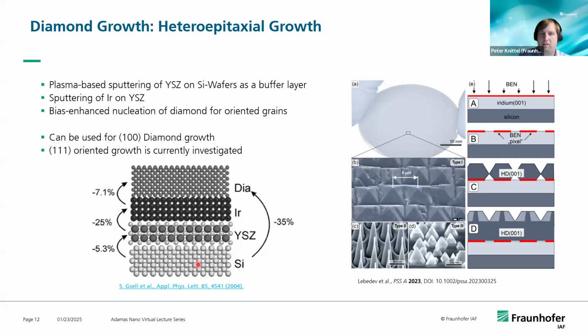There is another company in Japan that makes use of a bit of a different structure, but the idea is always similar, using this bias enhanced nucleation, forming oriented grains. And with that, you can produce 100 oriented diamond wafers. I think Diamond Foundry recently showed that this can even lead to 4-inch single crystalline diamond wafers. We also have an active project that tries to achieve growth of 111 diamond wafers, which is a bit more challenging. But this is also possible, and it has some challenges.